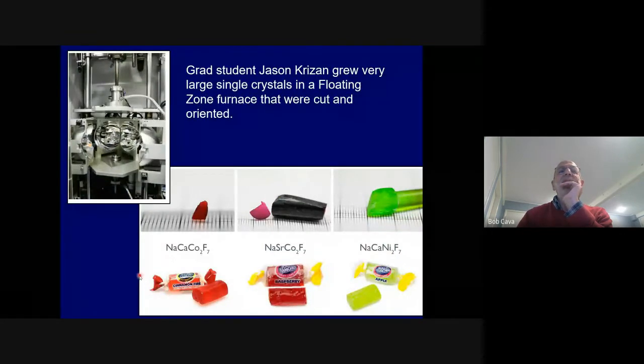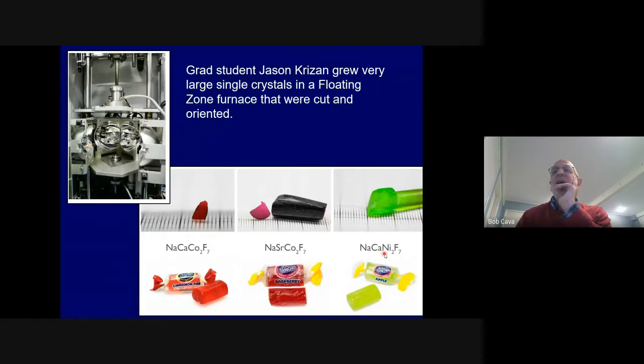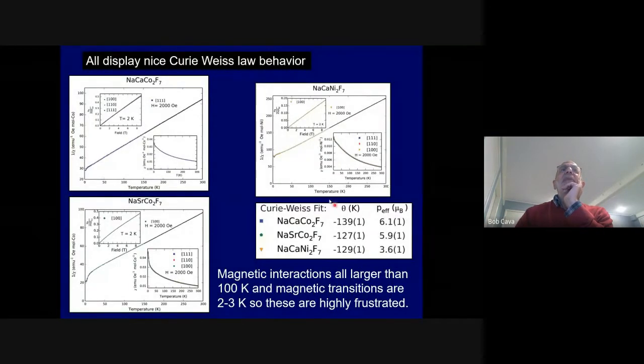And these were grown in a floating zone furnace by my student Jason. And they are insulating pyrochlores with two sites disordered on the A sublattice and the magnetic atoms being divalent transition metals. We'll see that this disorder probably has something to do with it. You can grow gigantic crystals of these in a floating zone furnace, so they're suitable for neutron diffraction. Here is a beautiful plot of the 1/chi behavior, 1 over the susceptibility behavior, of sodium calcium Co2F7, which is now a pyrochlore. The slope of this line tells you the magnetic moment of the magnetic element, and the temperature intercept tells you something about the strength of the magnetic interaction. And now you can see that the intercepts are large.